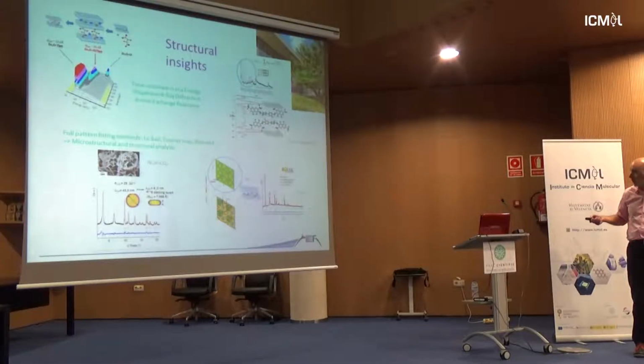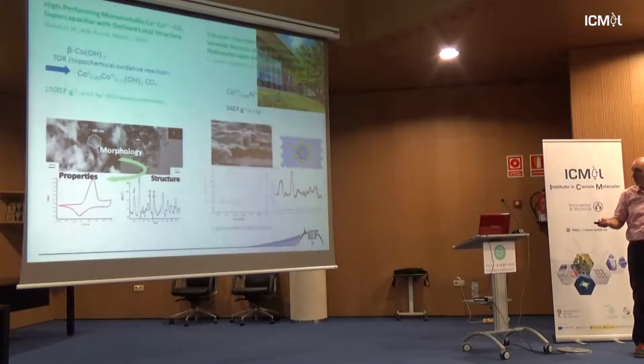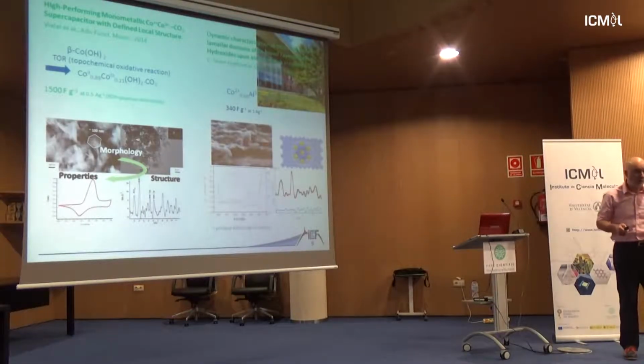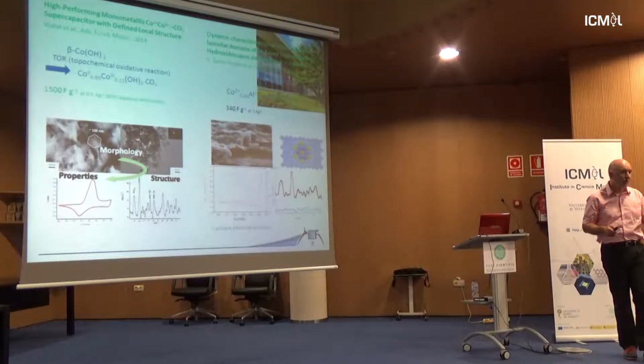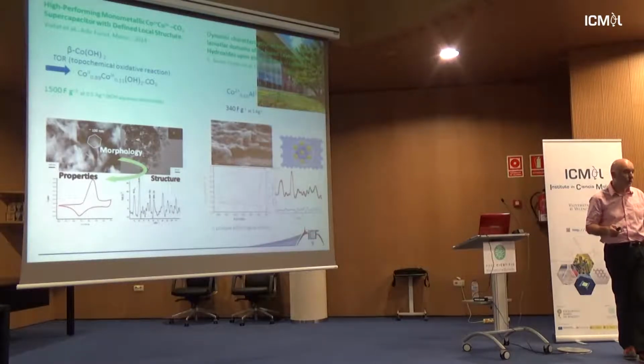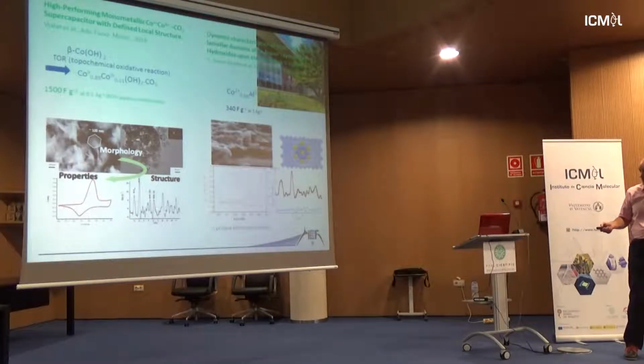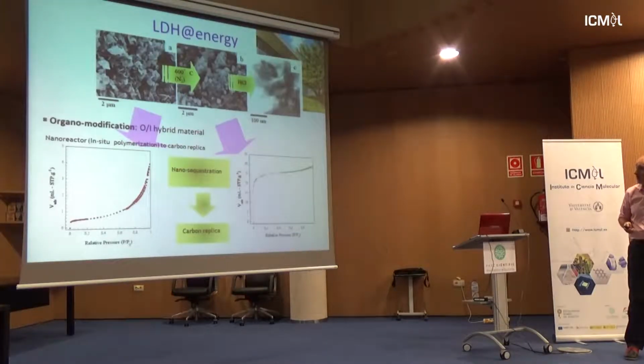You go down to more than 120 in the inverse space, and you can get such information. So that's very important. And when you are looking at, for instance, neighboring magnetism centers inside the intra-layer, you may have some very clear information on the local order. So that's been done on these topics.